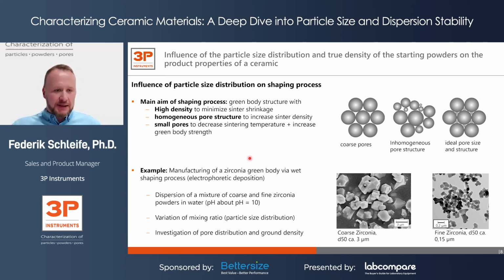For this, I want to give you an example. I want to show you the manufacturing of a zirconia green body via a wet shaping process, a so-called electrophoretic deposition. Therefore, there was a dispersion of a mixture of coarse and fine zirconia powders in water with a pH value around 10. And there was a variation of the mixing ratio of fine and coarse zirconia powder. It could be investigated by the pore distribution and also the density how different ratios and mixtures of coarse and fine zirconia would affect the final process.